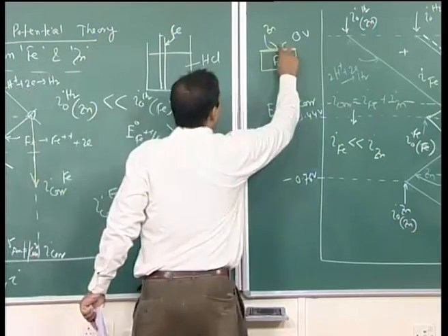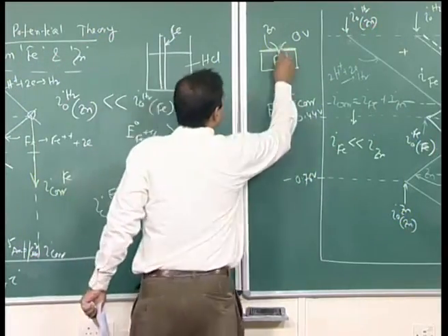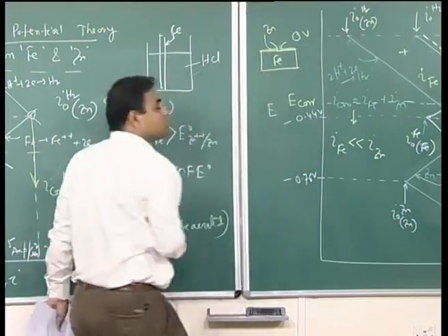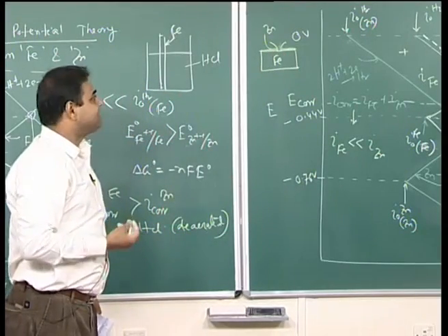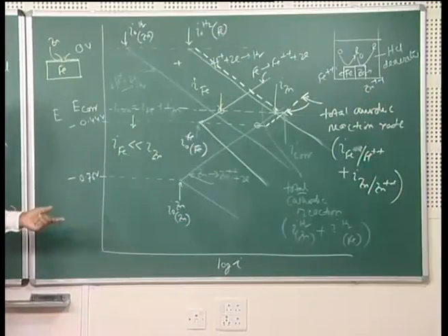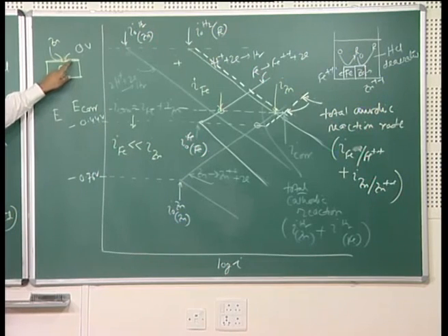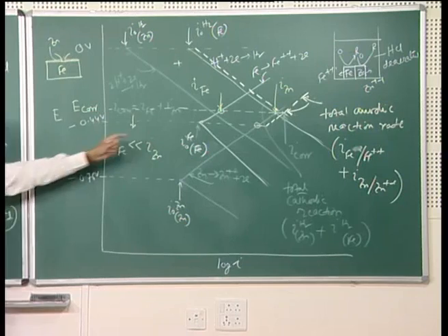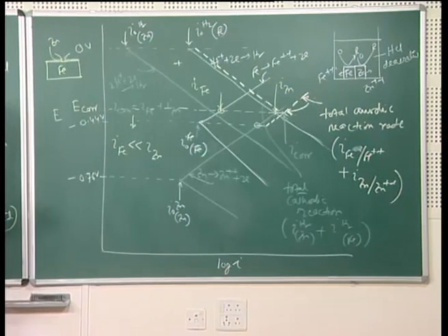Now, you are coming across all those corrosives in the environment. In that case, coupling will happen between zinc and iron, so zinc will preferentially corrode, and iron corrosion rate would be less, as we see from here. This is an important understanding, and that is why zinc is used for galvanization on iron surface.